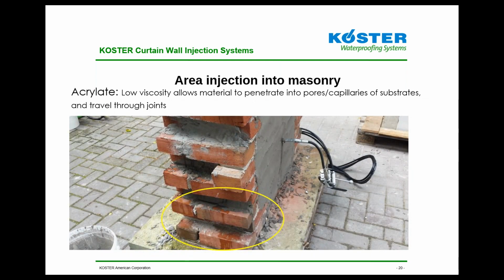For area injection, acrylates are always chosen over polyurethane products. Low viscosity of the material allows the acrylate to penetrate into the finest pores, voids, and capillaries in the masonry and in mortar joints, which flows and creates a barrier. Towards the bottom of the picture here, you can see the acrylate material running out of the sides of the prop with the injection port about 1.5 feet away. So you can see that material is so low viscosity, and when it's pressure injected, you can see how it flows through every single capillary and void and creates that barrier within the substrate.